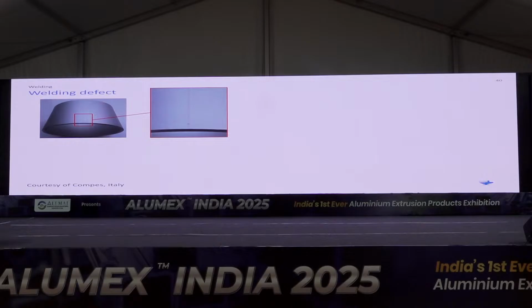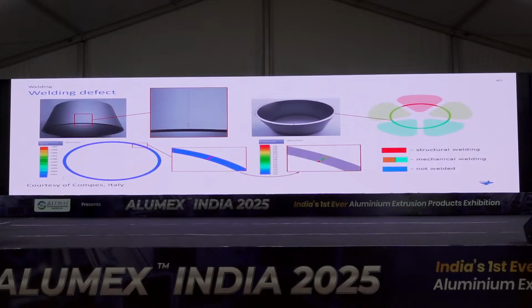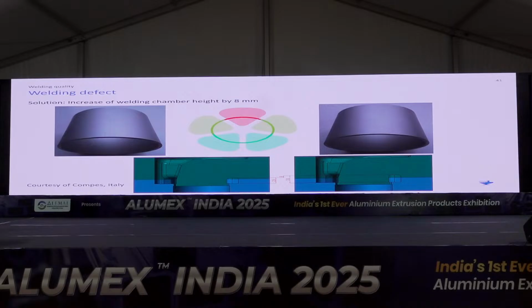So there is a case study with a simple tube where you can see a welding line all along the extrusion. Here we can find the position of this welded line, and also the values of the criterion. You can see that the value is lower than 1, which means that this weld doesn't have a structural welding. Here we can see what typically can be done when you start to optimize the design. Typically, you will try to provide more pressure under the web, but the issue is that if you do it too much, you can break the die or your profile will be out of tolerances.